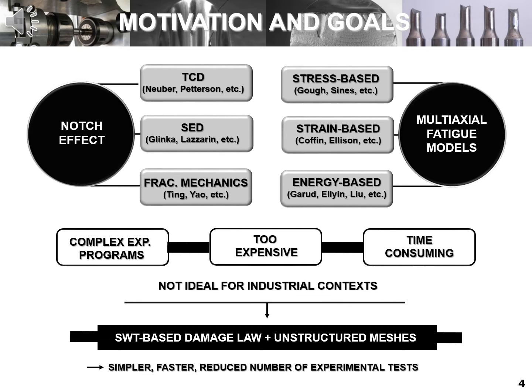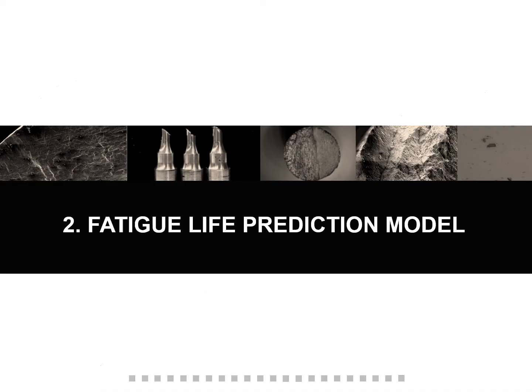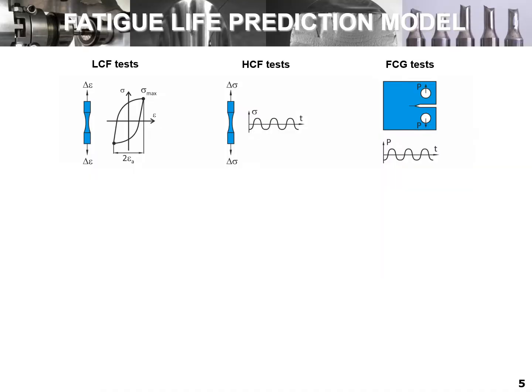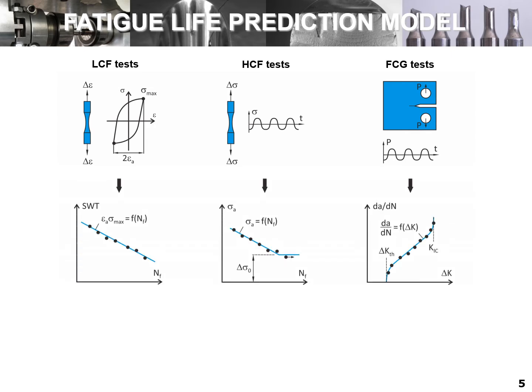In this study, we propose a simple approach based on a limited number of material constants and a rapid and unstructured finite element mesh, implemented using a linear elastic framework. As far as the fatigue life prediction model is concerned, the first step is devoted to the material characterization. As shown in this slide, we performed low cycle fatigue tests, high cycle fatigue tests, and fatigue crack growth tests.